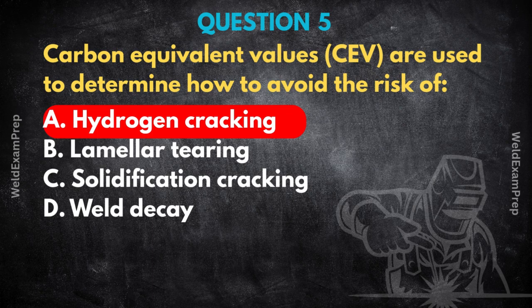To slow the cooling again. Precisely. Higher CEV generally means you need a higher preheat to slow down that cooling, allow hydrogen to escape, and avoid forming too much martensite. It's all about mitigating that risk of hydrogen cracking before it starts.